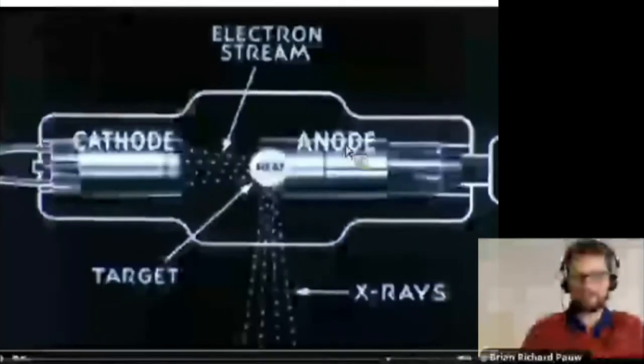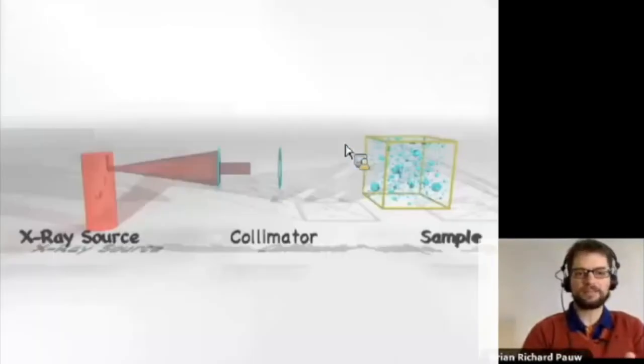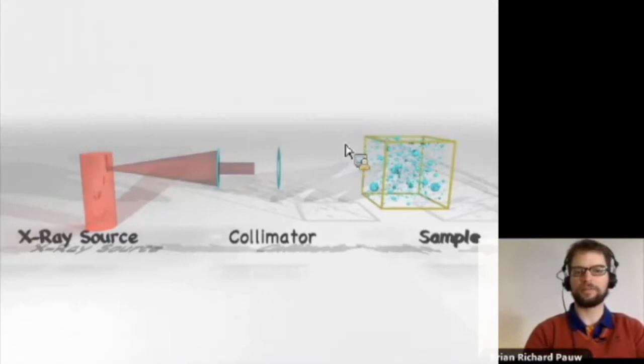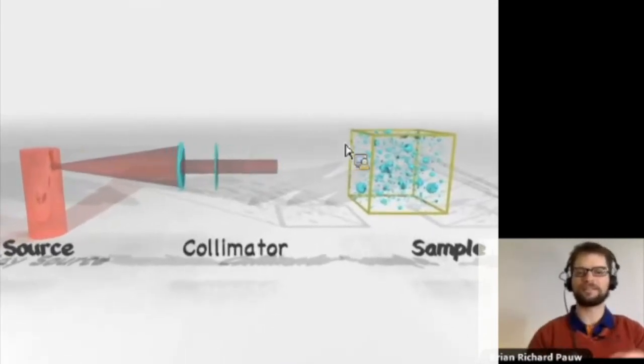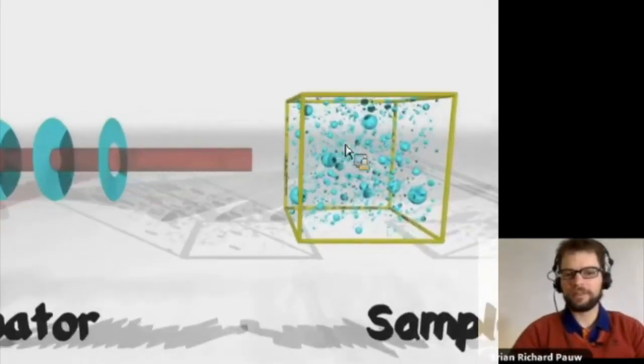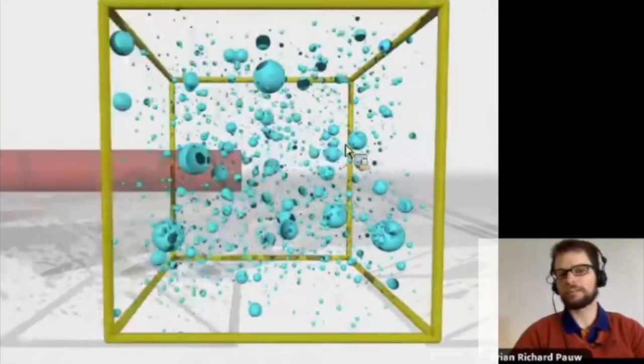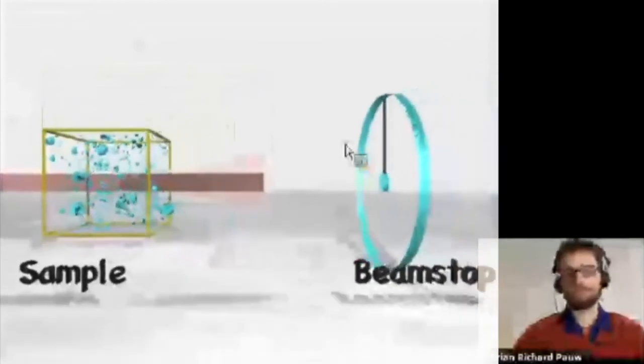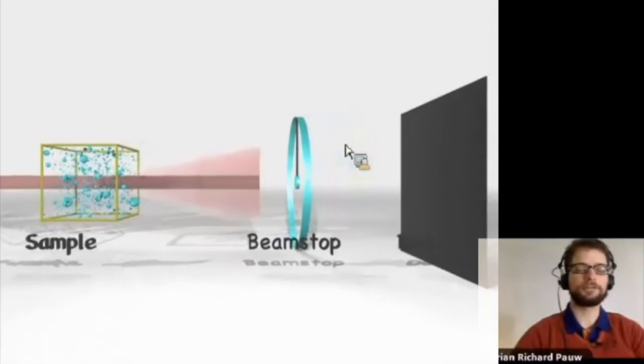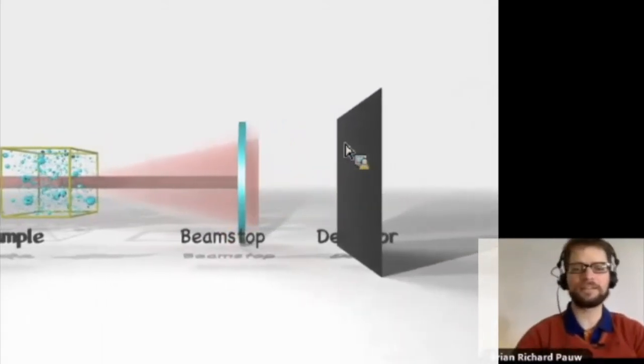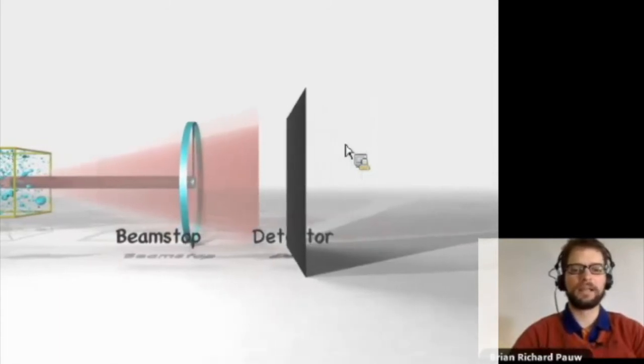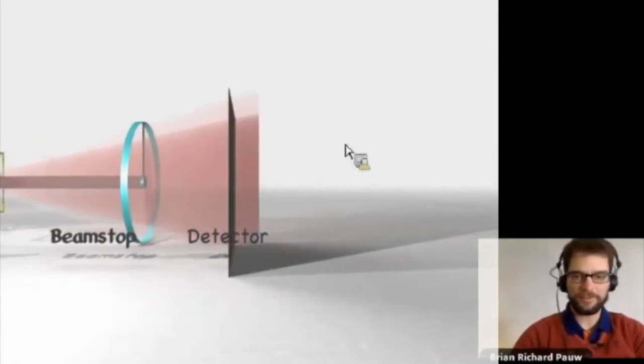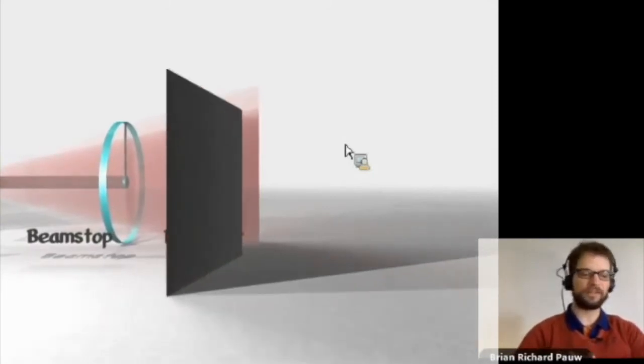So once we have that X-ray source, we then monochromate the X-rays. So we pick out X-rays of one particular wavelength. And we then send that through a collimator. And the collimator cuts down our X-ray beam to a size of about 0.5 millimeter in diameter, or less than that. After which, electron density differences in our sample will cause a small fraction of the X-rays to be scattered. We stop the unscattered beam using a beam stop so that it doesn't overload our detector or disrupt our signal. And we collect the scattered radiation on the detector. And in practice, the experiment is really as simple as this. But as I mentioned, it is really hard to do this experiment right.